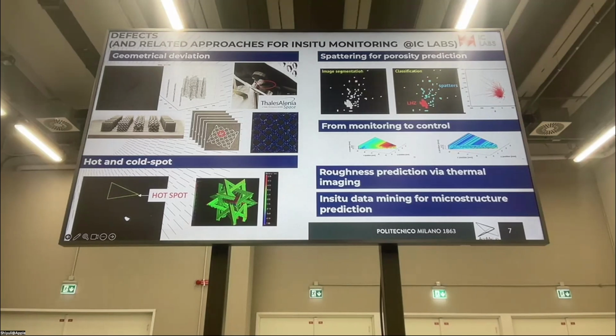Spattering is a quite interesting phenomenon. Again, there's a lot of research going on to investigate the shape of all these spatters that are coming out from the melt. Depending on the type of spatter signature, you can have porosity at the end. We've also been spending some time moving from monitoring to automatic control. So once I see something is wrong in a layer, I can even react and compensate with the process parameters in the next layer, just to heal the product while it is being machined.